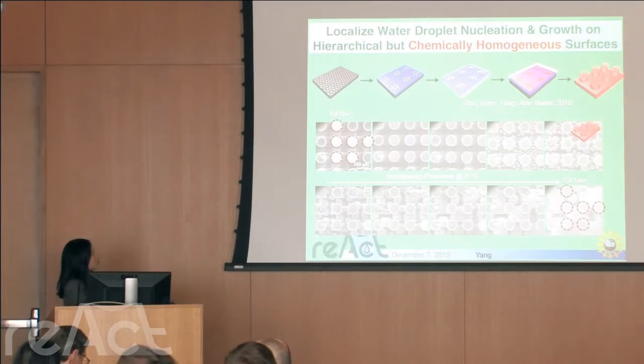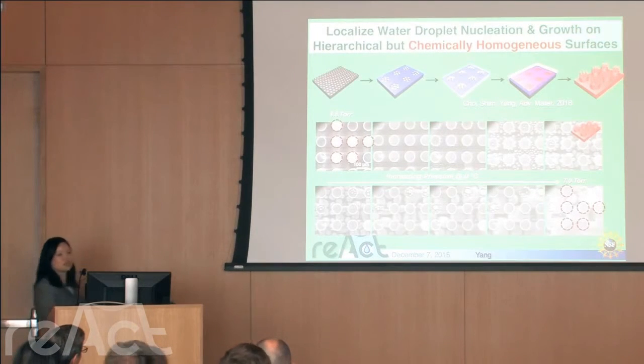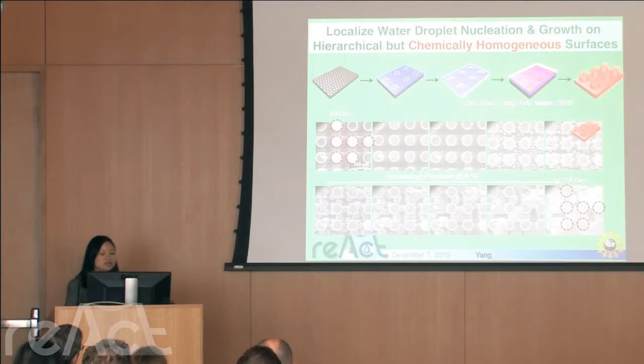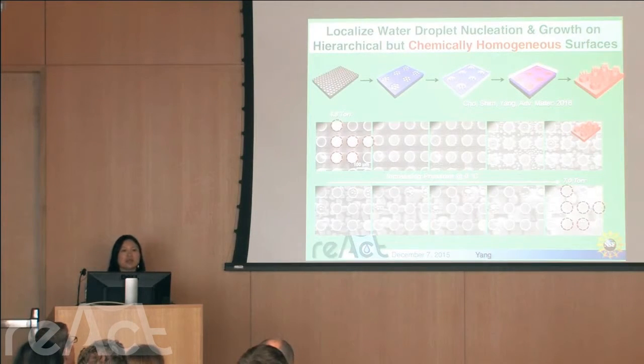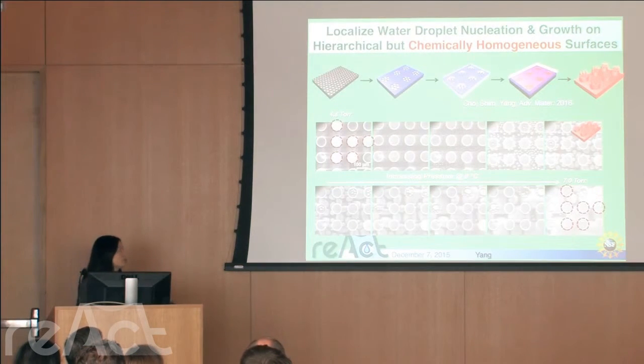So for example, Yonghong Chang in my group used this AAO template, anodized aluminum oxide, as a template. And then we coupled it with photolithography, and we introduced these hierarchical structures on the surface. So I have micropillars on top of it, and we have nanopillars. All right, so our question is, can we use this to either encourage or discourage the water nucleation?